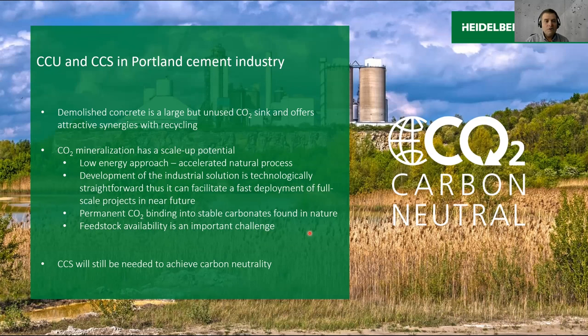And I show you that demolished concrete, and particularly the recycled concrete paste out of the demolished concrete, is a potential important sink of CO2. CO2 mineralization has a big scale-up potential. And this is, for example, a low energy approach, since we are able to conduct the reaction rapidly and with high hydration degree at normal temperature and pressure. And this gives us promise, partially confirmed during our industrial trials, as I showed you, that this kind of technology has a high potential for industrial application.